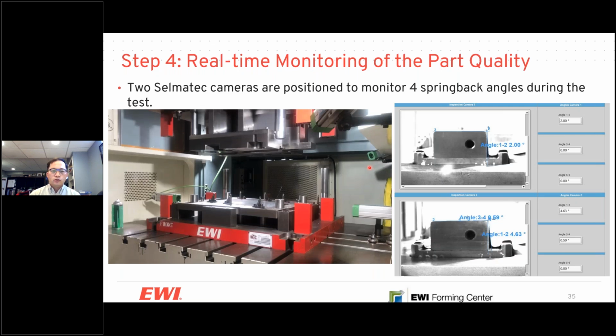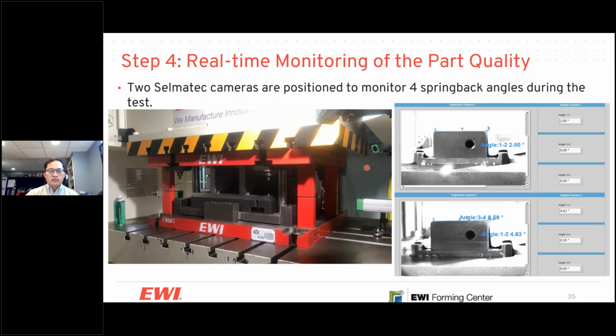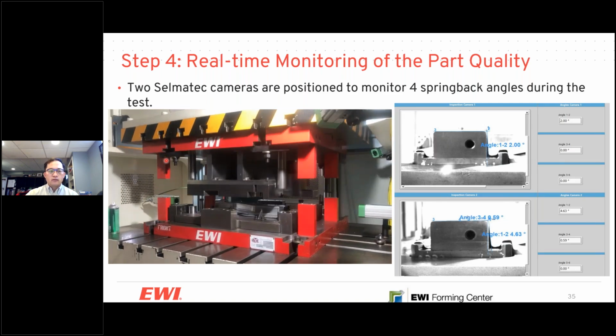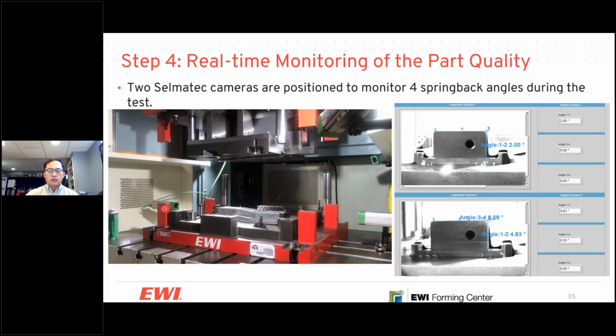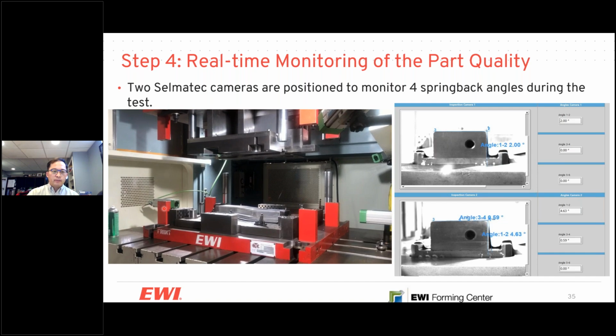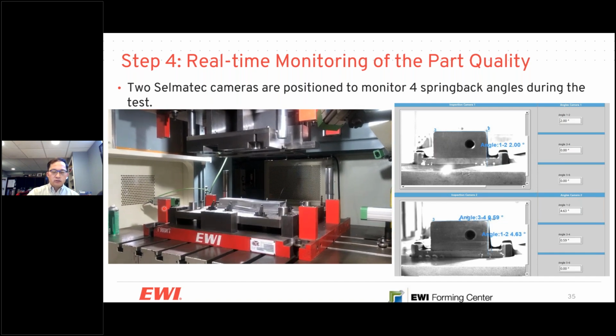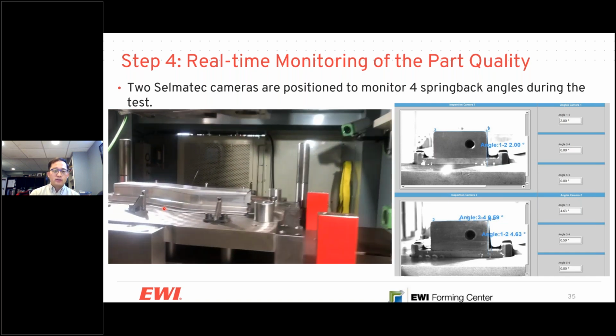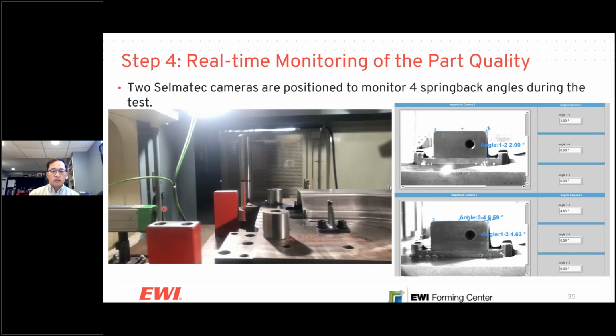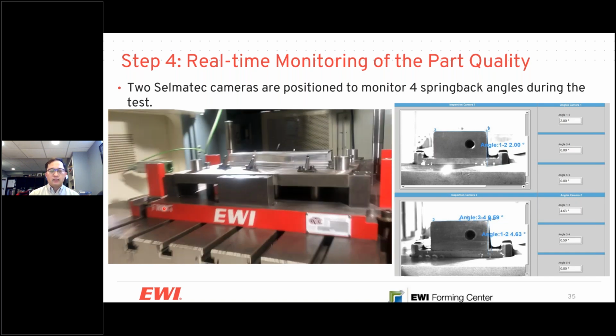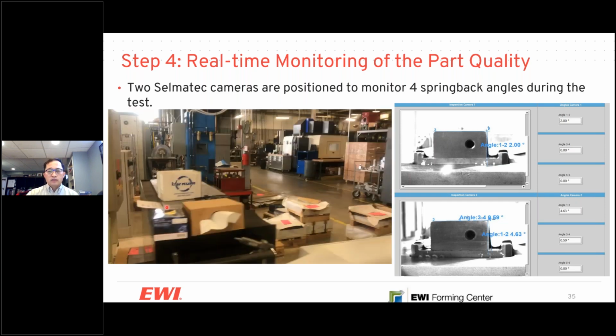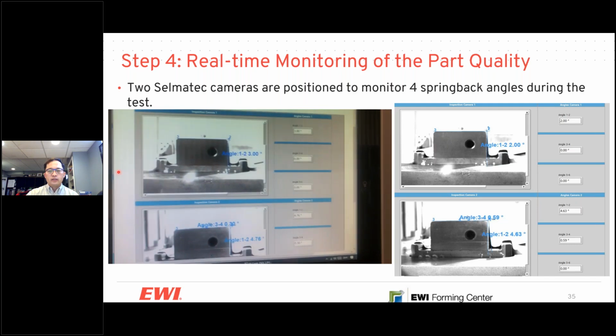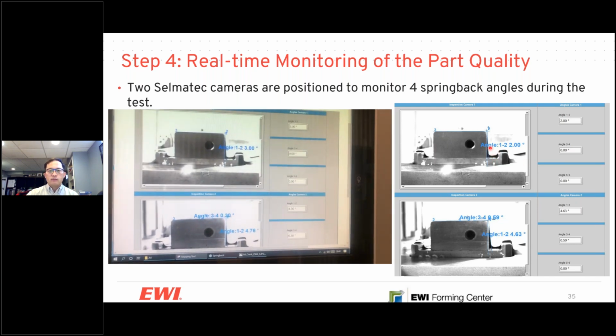Now, one thing that I want to show you here is that we also use a camera system. We actually measure the springback angle right on the die. We don't need to take the part and put it in another inspection system or fixture to check the springback. So we can get the springback data from 100% of every single part that we stamp in our press. The image on the right is a snapshot from that camera system, which measures the general opening angle, as well as the twist angle and the lift-up angle, which relate to the twist amount of the springback of this S-rail tool.